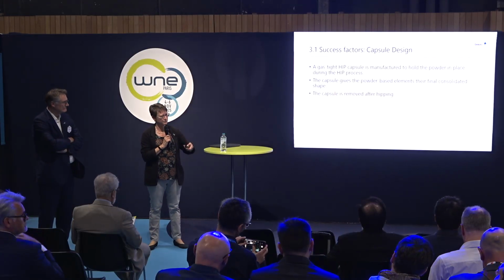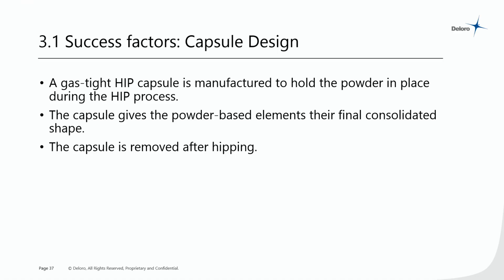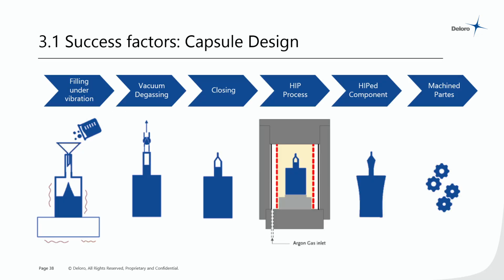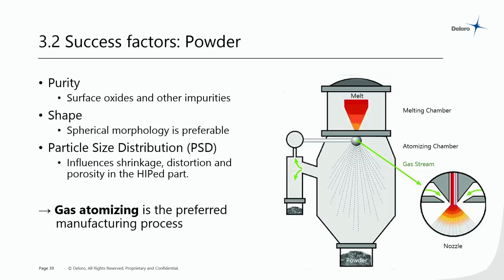So the capsule design is important because the capsule has to be gas tight. It holds the powder in place during the HIP process. It gives the powder-based element, particularly in bimetallic HIP, its final consolidated shape, and it's removed after HIPping. Here you can see a little schematic of how a capsule is filled under vibration, vacuum degassed, closed, HIPped. You can also see schematically the distortion represented there, and then the final machining to get your final part.